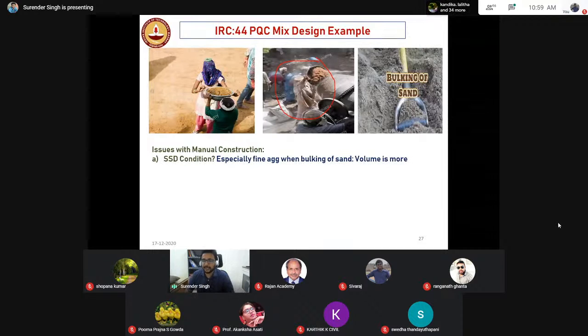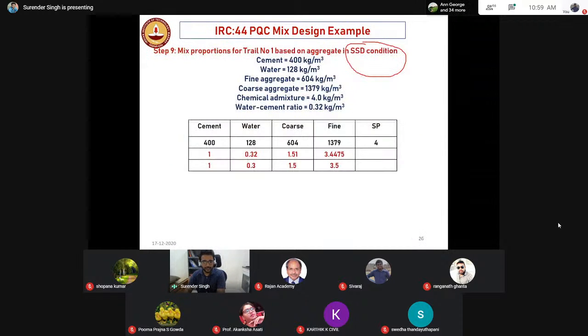And second thing is, can you achieve SSD condition in the site? No. Because SSD condition means you have to completely soak the aggregates with water. For coarse aggregate, you can do it, but for fine aggregate, it's nearly impossible. That's why at the site, we are using the aggregates in dry condition. Now, the mix design that you did is in SSD condition. How to convert this SSD condition into dry condition?